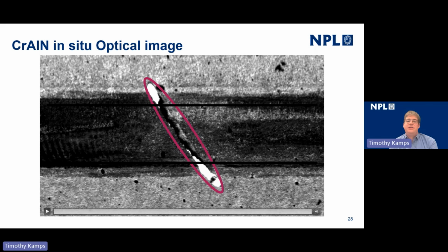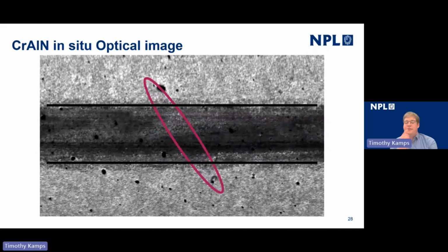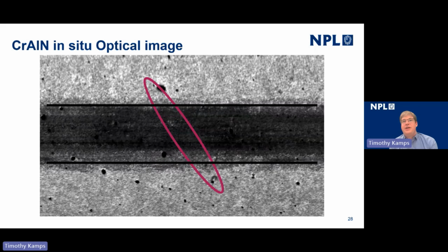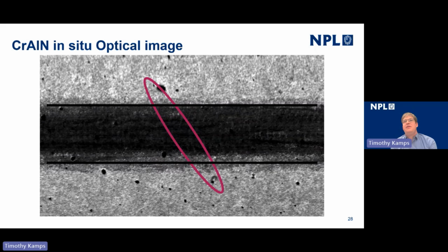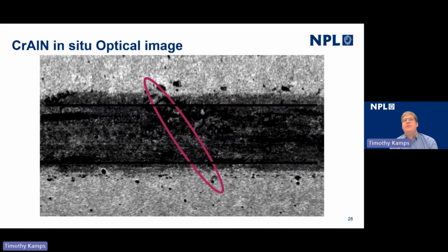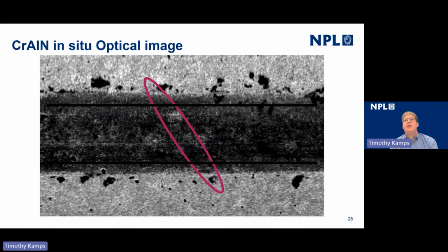So as the video played, you saw the formation and removal of CrAlN film on the surface. You can see it growing to a critical thickness. You can see it being removed from the surface and then it growing again, and the change in the wear track width as that silicon nitride ball wears a flat on the surface. What's quite interesting to note is that once the coating fails, the recess that's left in the surface very quickly fills up with debris that's formed from the sliding contact.